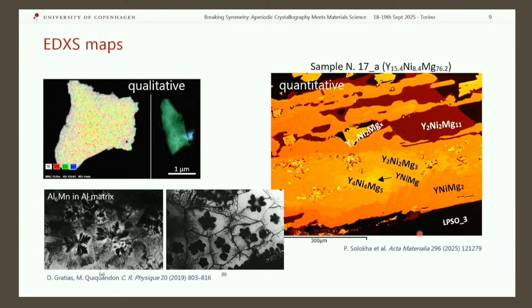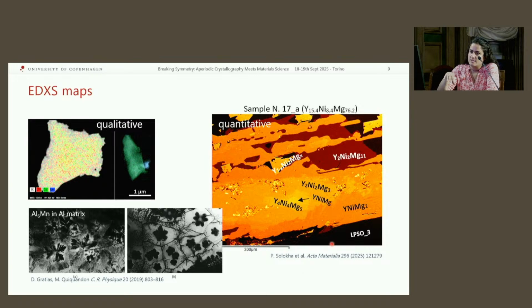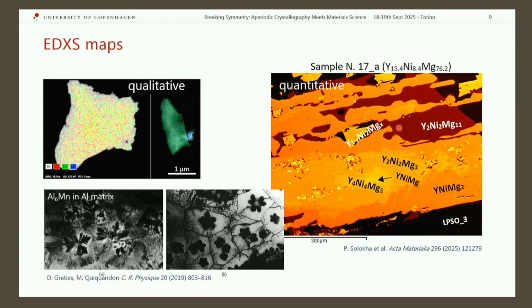And because we can precisely control the position of the beam and make it very small, we can scan the beam over an area, and basically we collect the EDX pattern for every pixel of the image, so we can make a map of where the elements are, so we can see if the crystals are all the same or if they have different composition, for example. And if we do the quantification, we can see in a bulk sample where the domains with the composition that we are interested in are. It could be a new composition, and that's, again, throwback time when we found the quasi-crystals in a matrix of aluminum, right? So now we can choose where to do our further analysis, in which region.